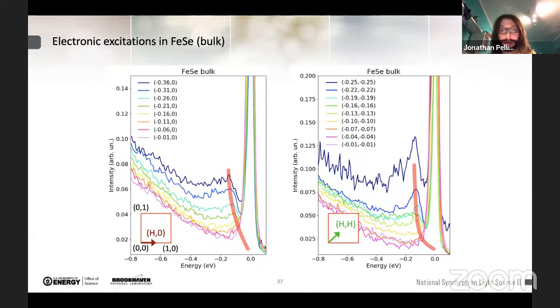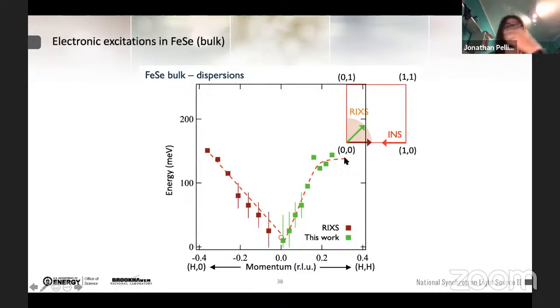Here, I'm summarizing the results for the dispersion of the iron selenide bulk. So I'm plotting the energy as a function of momentum along the Q, along the two crystallographic directions that we have monitored. And you can see that we have a spin excitation dispersion that resembles the classical spin waves.